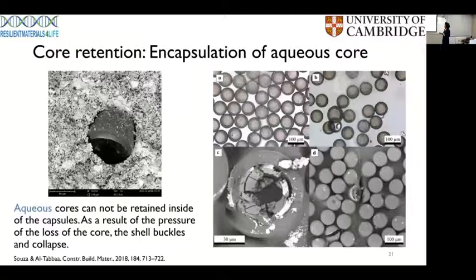But that per se is not the biggest problem. The problem is that sometimes when that water is coming out of the shell, the capsule may buckle as well. And it's a much bigger problem when we are talking about the loss of that aqueous core.